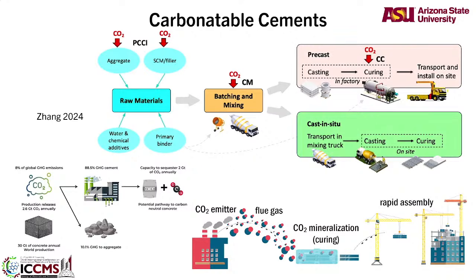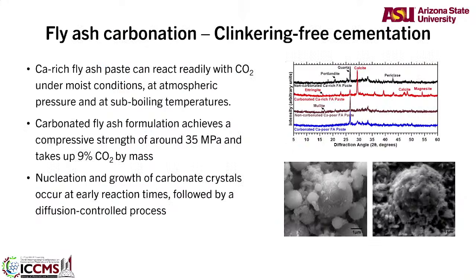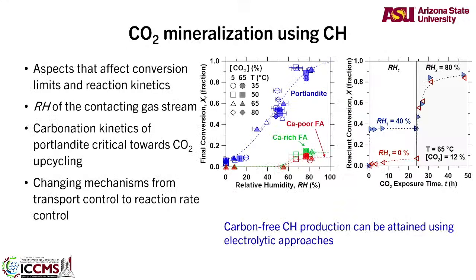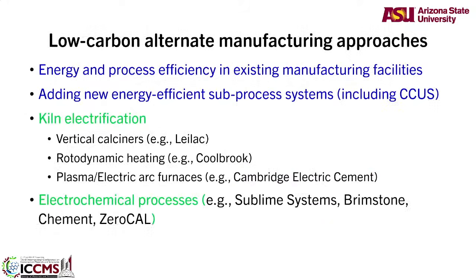You can carbonate cements. You can make cements carbonate and then absorb some CO2 that way. You can use fly ash to carbonate stuff very, very well. Those who are working with alkali activated cements, they'll carbonate even more. Don't ask me if carbonation is a problem here. That's a totally different story. For this, carbonation is different from the carbonation for concrete that causes steel corrosion. That's a different story. But you can create carbonated products. You can mineralize it.